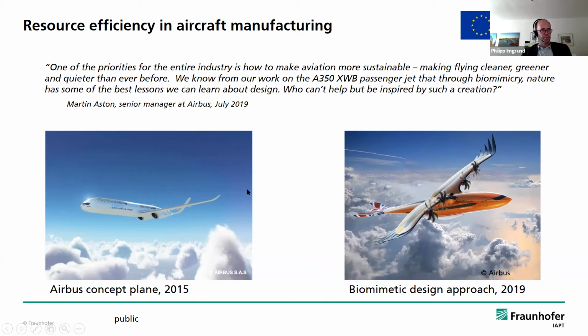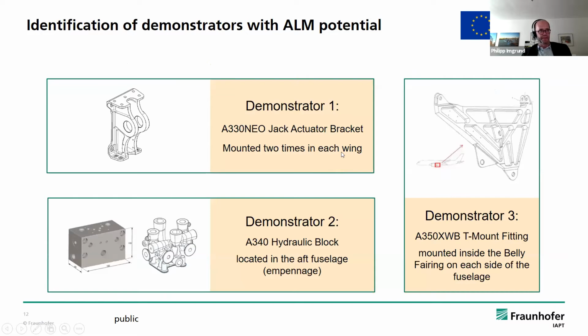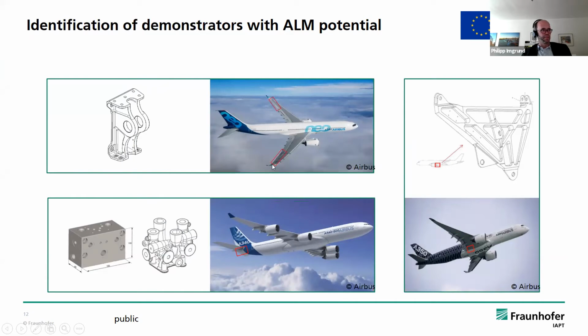I want to show you some components that we designed and which we developed during this 3-year adventure that we had. And we identified from the Airbus A330 a jack actuator bracket, from the A340 a hydraulic block, and from the A350 a big T-mount fitting which supports the wings. You can see the location of the demonstrated components. So the actuator bracket is actuating the flaps here. The hydraulic block is here in the rear of the aircraft, and the T-mounting fitting is really in the inner structure of the aeroplane, supporting the wing structure.